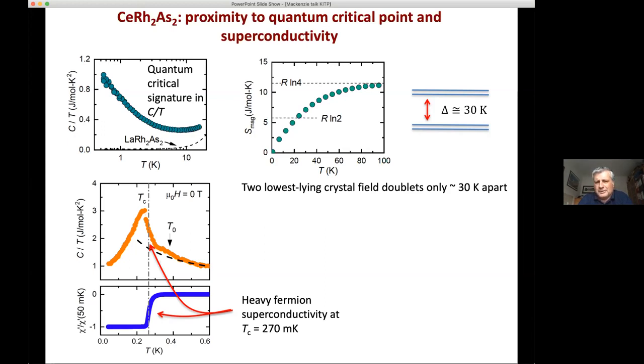What I really wanted to do today was to convince people that this is a real and interesting superconductor to add to the pantheon. A question from Daniel Khomskii about the lowest crystal field doublet, which probably plays the most important role at low temperatures: if described by effective pseudospin, what kind of properties does it have — dipole, quadrupole, or octopole? Daniel answers: in terms of local C4V representations and double group representations, this doublet is a gamma-7 representation, which has the same properties as a spin-1/2 system — the Pauli matrices in this doublet have the same symmetry properties as usual spin X, Y, Z operators.